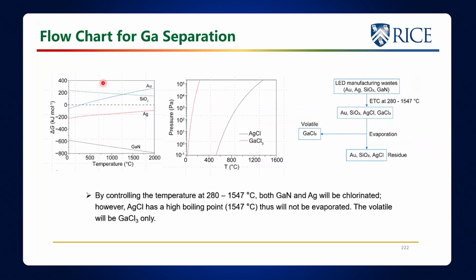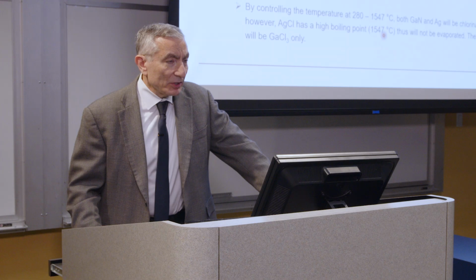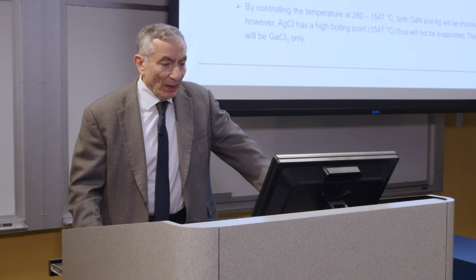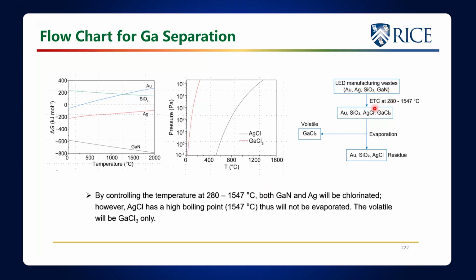And then if you look at the thermodynamic chart, you can see that both silver and gallium nitride should spontaneously come off under the chlorination reaction at any temperature. It doesn't matter the temperature, they're always less than 0. But if you look at the boiling point, gallium chloride boils much more easily than silver chloride. Silver chloride doesn't boil until 1500 degrees. So we should be able to separate this just based on a very simple evaporation. So you take the LED waste, you do this electrothermal chlorination, and that's going to make silver chloride and gallium chloride. Gallium chloride evaporates out, and you have silver, gold, and silicon oxide in the residue.